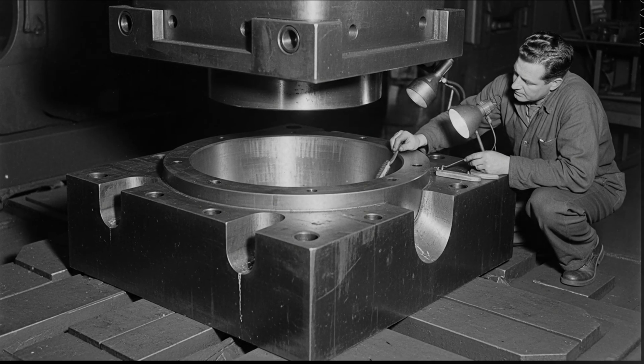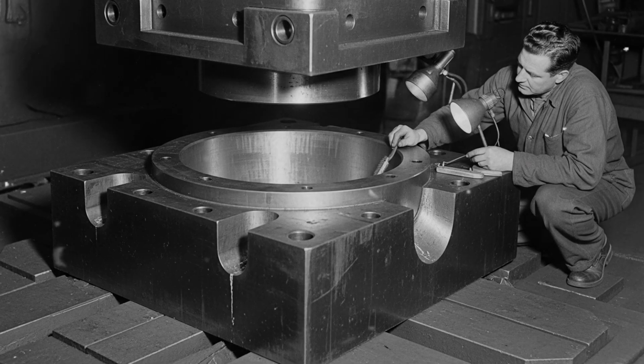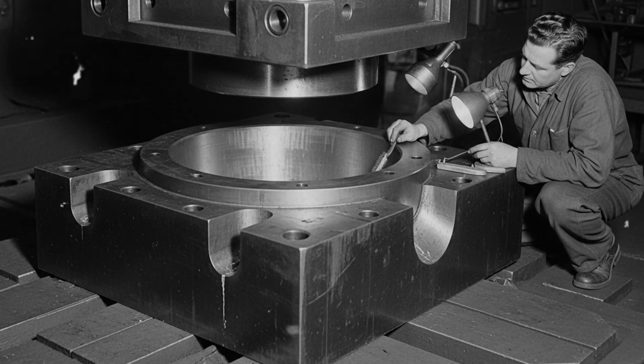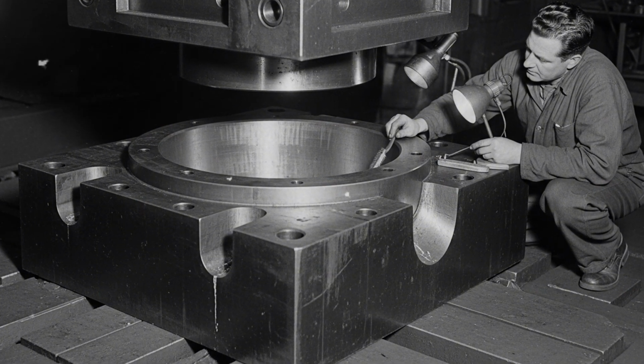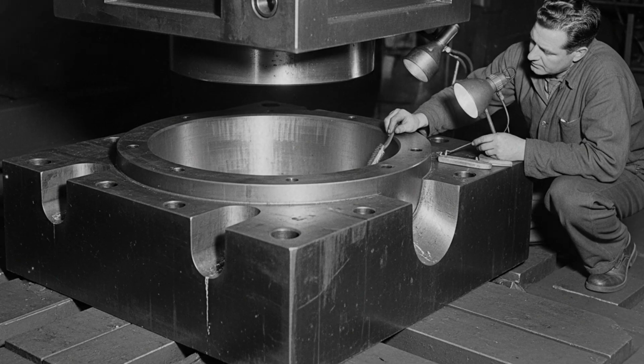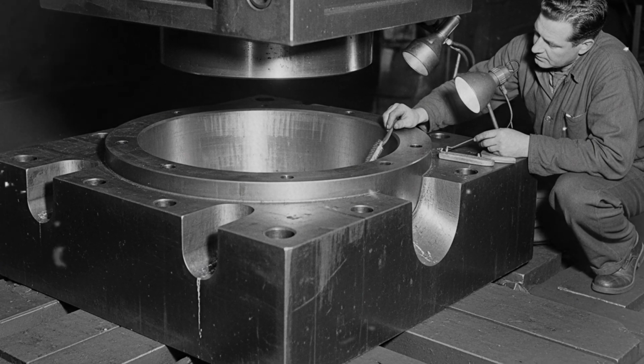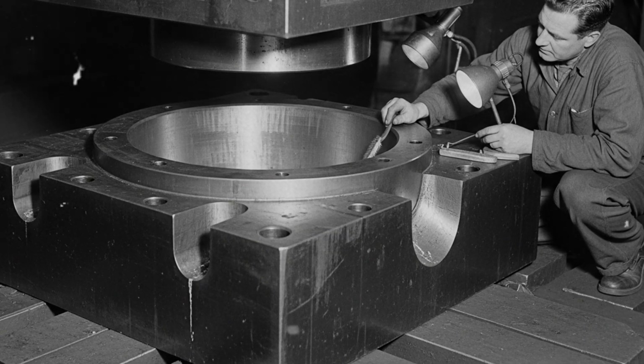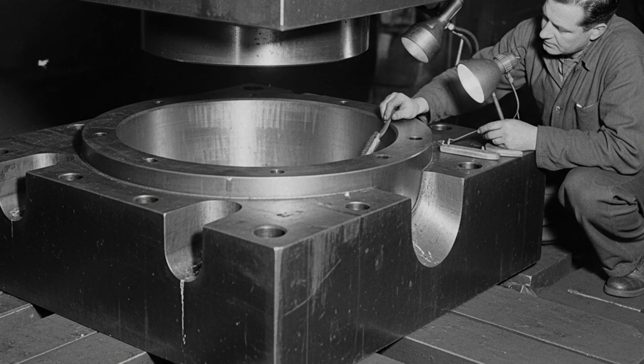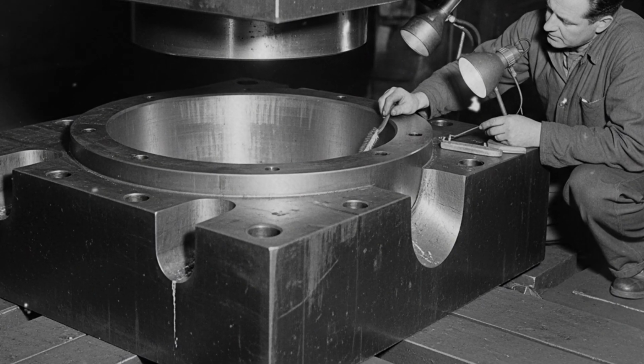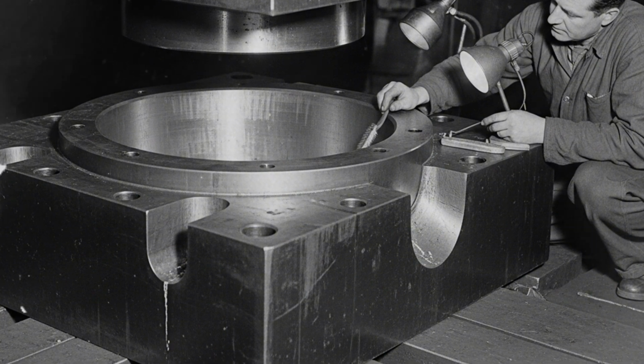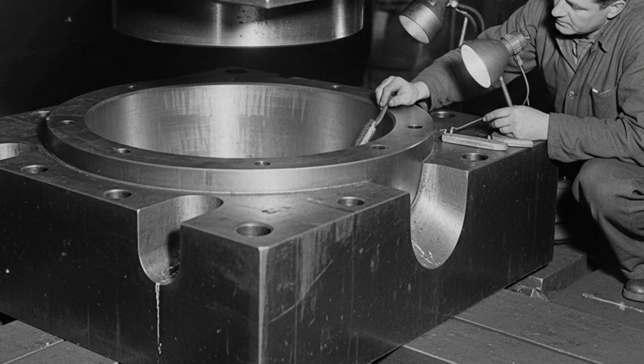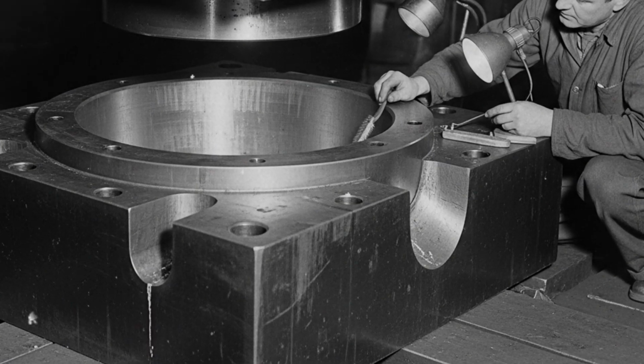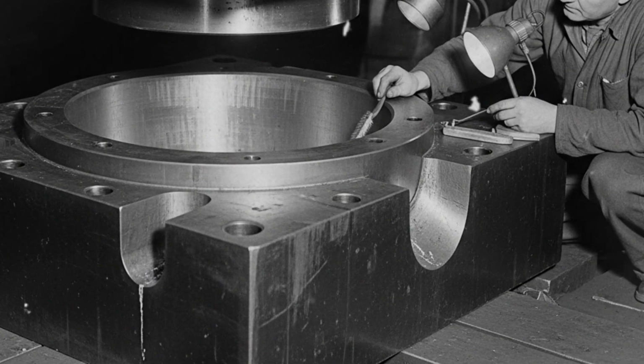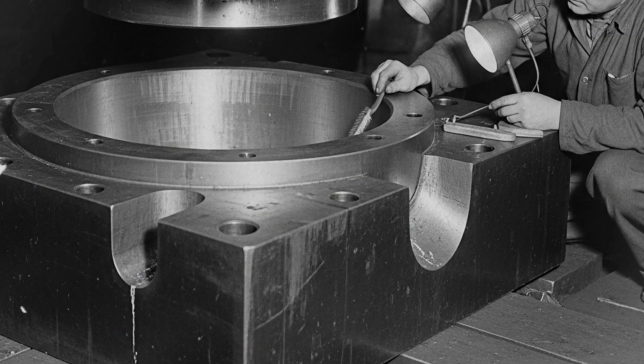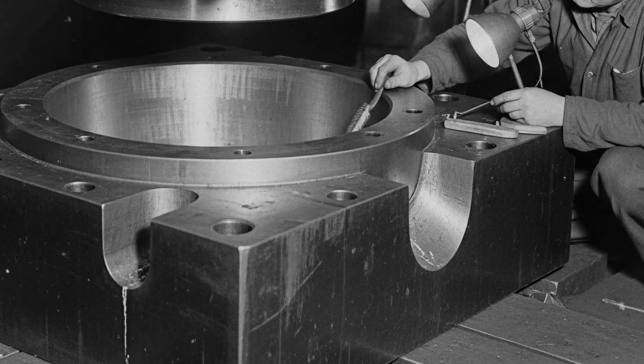The die systems used in these presses deserved particular attention because the die was where the machine's force met the material and where the most precise and most dangerous work occurred. A forged die for an aerospace structural component was itself a precision engineering artifact. Machined from H13 tool steel, a chromium molybdenum vanadium alloy capable of withstanding repeated thermal cycling without surface degradation, a single match die set for a major structural forging could weigh 40,000 pounds and require 6 months of precision machining to produce. The die cavity defined the finished geometry of the forging with tolerances measured in thousandths of an inch.